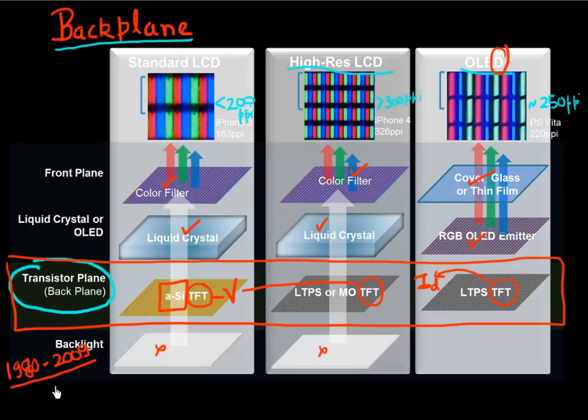The problem with amorphous silicon is that since it's an amorphous material, it does not have a very high mobility. The maximum electron mobility that you get in amorphous silicon based display is around one or two centimeter square per volt second. This was fine when you had low resolution display or you were not refreshing your display at a very high rate.